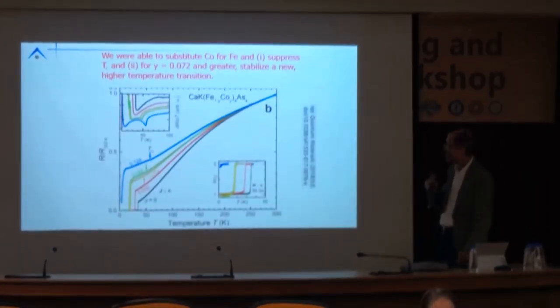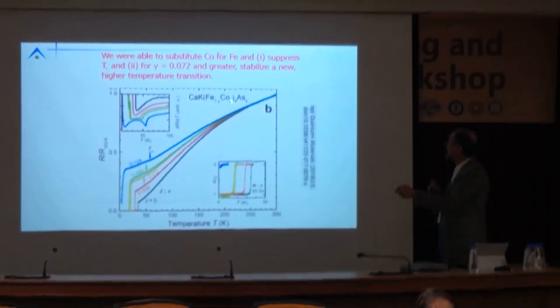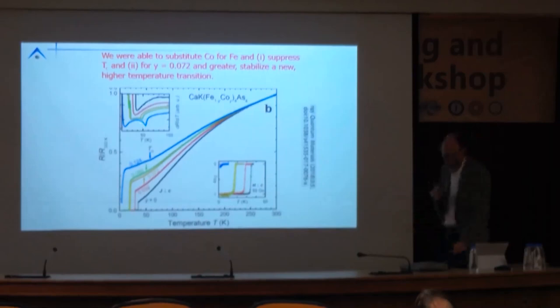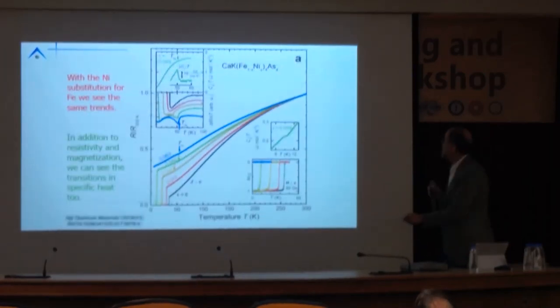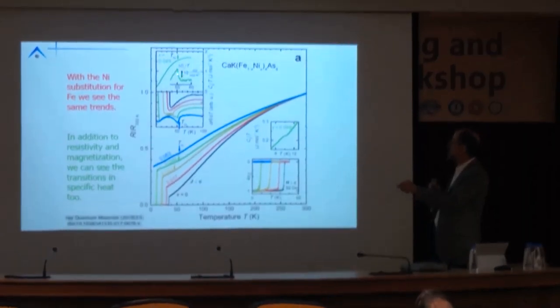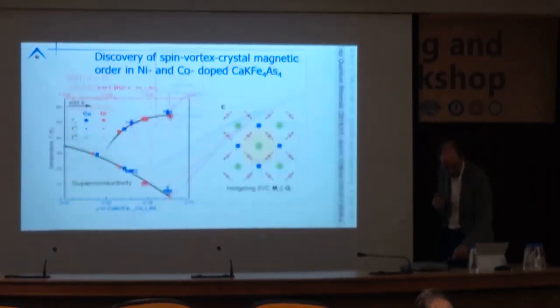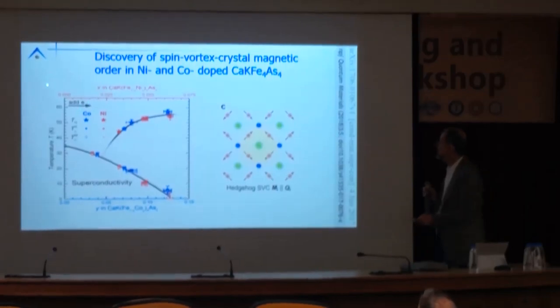Okay. We can keep going. All right, so as we add cobalt, we suppress superconductivity. We can see that in resistance, we can see it in magnetization, and beyond a small amount of cobalt, we see a new feature coming in the resistivity. We can do the same with nickel. Again, as we add nickel, we suppress superconductivity in resistivity and magnetization and specific heat. We can see a new feature coming in at higher temperatures in resistivity. We can detect it in specific heat. And we can assemble a phase diagram.